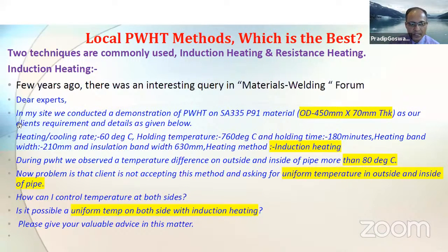He says, "Dear experts, at my site, we conducted a demonstration of post-weld heat treatment on grade 91 material. It was 70 millimeter thick. Our client's requirements are given as below. This was the typical heating and cooling rate the client insisted on. This was the holding temperature, and this was the holding or soaking time. The heating bandwidth and insulation bandwidth, everything was specified. The heating method was induction heating. During the post-weld heat treatment, we observed a temperature difference between outside and inside of the pipe that was more than 80 degrees centigrade. Now, the problem was that the client was not accepting this and was asking for uniform temperature on the outside and inside of the pipe. How can I control temperature on both sides? Is it possible to have a uniform temperature on both sides with induction heating? Please give your valuable advice in this matter."